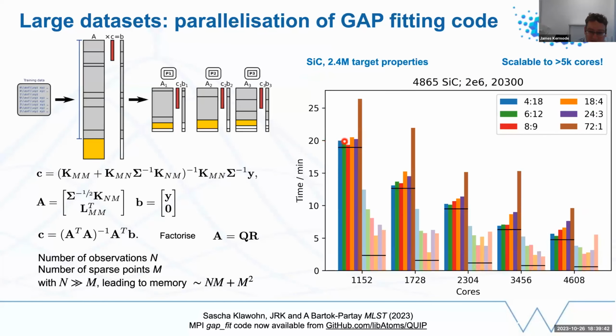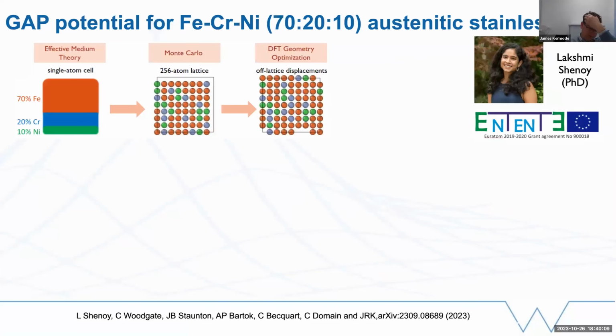Most of that speed up is actually coming from descriptor and covariance evaluation. So by building these different parts of the matrix in parallel, we can trivially fill them in parallel, and that doesn't require any communication at all. So we get a big speed up moving through these dark shaded bars as we increase the number of cores. The speed up in the linear solve is smaller, and that will saturate at some point. So you can see that on average, that's only improving a little bit, but the overall speed up remains good.